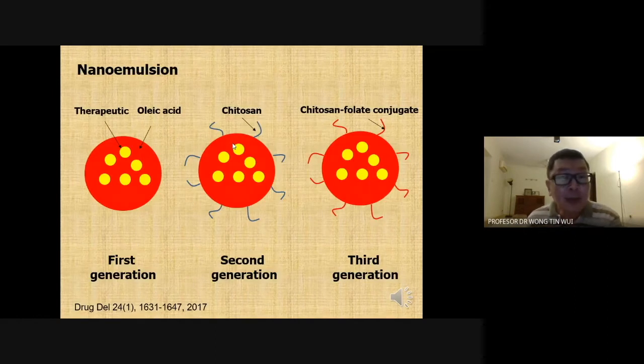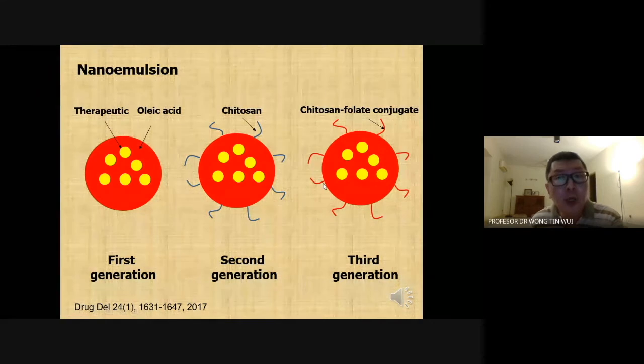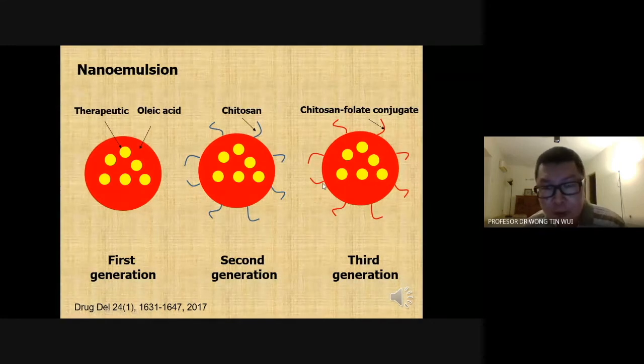Now, in another experiment, we also looked into inhalation of liquid medicines such as nano emulsions. We actually developed 3 generations of nano emulsion. Now, the first generation is very simple. It's just an oil and water emulsion with the therapeutic dispersed in the oil globules of oleic acid. Now, for the second generation, we began to advance the design. We decorated the oil globules with chitosan. And for the third generation, we developed the oil globules with a chitosan-folate conjugate.